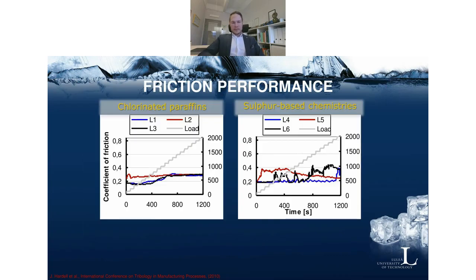Just as an example, the chlorinated paraffins work really well with stainless steel surfaces. So we have 3 different formulations called L1 to L3, and this is during a load ramp test on the left side. So you can see that we have not extremely low friction, but at least it is repeatable and stable.